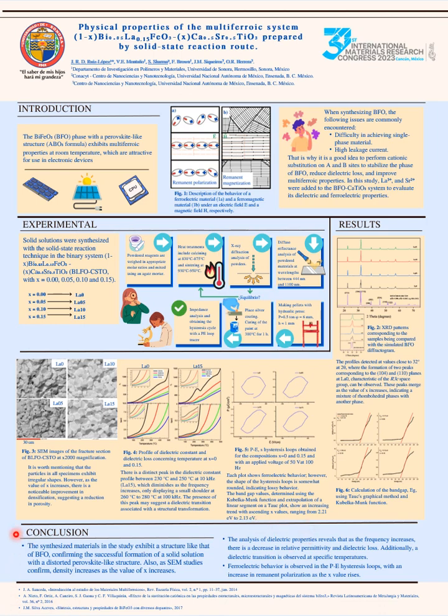In conclusion, the synthesized materials exhibit a structure like that of BFO with X equals 0.0. But with higher values, it seems a mixture forms between rhombohedral phases and another phase. Furthermore, the dielectric and ferroelectric measurements indicate some improvement as the value of X increases, but with leaky behavior.